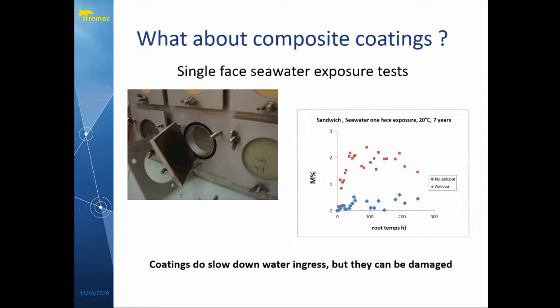And this is an example on the right for a sandwich material. So on the bottom, we have the material with the gel coat, and we're very close to zero. We have very little water getting in, although we do have some. And without the gel coat, we have probably going up to a couple of %, and we start to get some degradation. So coatings can be efficient.